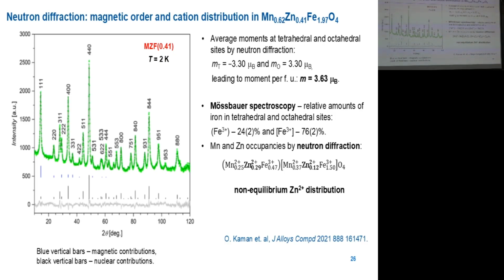There is another metal, and you cannot distinguish certain metals in XRD because they have very similar scattering factors. So you have to employ another diffraction technique, like neutrons, where the scattering factors of individual atoms might be quite different, and it will help to distinguish them. So by combining Mössbauer spectroscopy and neutron diffraction, we can completely describe the structure of such a system. We can exactly determine the amounts of individual cations on the tetrahedral and octahedral sublattices. And moreover, as neutrons interact with magnetic moments on the different atoms, we can also obtain some information about the magnetic ordering. We can resolve the magnetic ordering, and we can quantify the magnetic moments of individual sublattices.